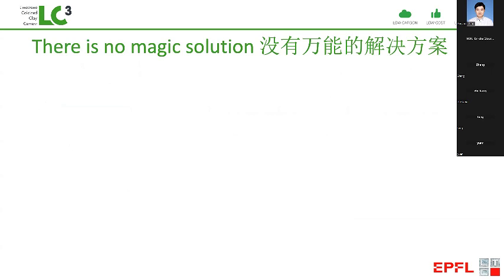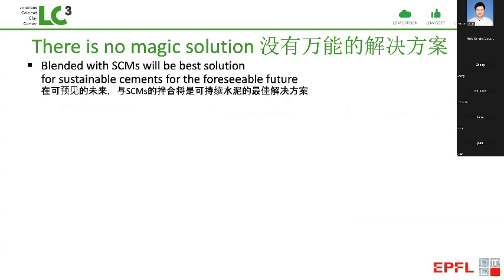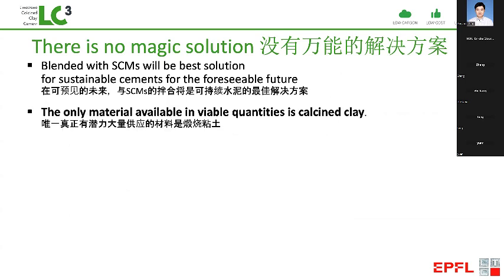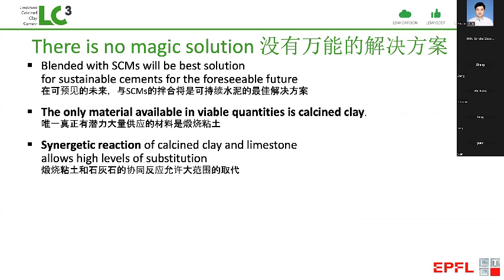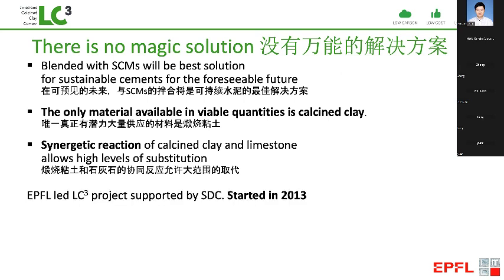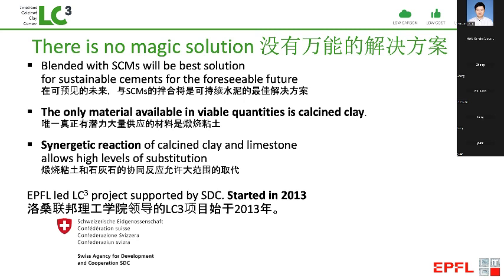So in summary, there is no magic solution. Blended cements with supplementary cementitious materials would be the best solution for the future. The only material available in viable quantities is calcined clay. And what we discovered, which is behind this LC3 technology, is the synergetic reaction of calcined clay and limestone allows you to go to very high levels of substitution. And this is the essential idea behind the LC3 project, which we started in 2013 and has been supported for the last 8 years by the Swiss government through their Agency for Development and Cooperation.